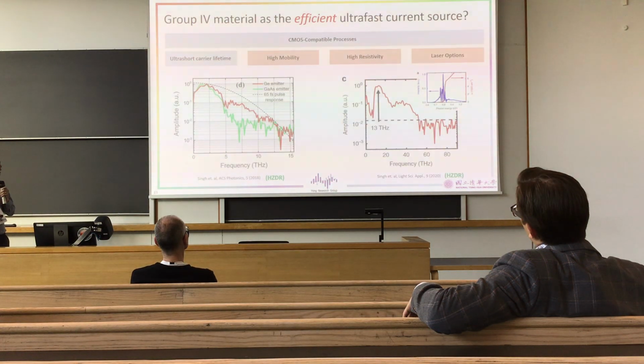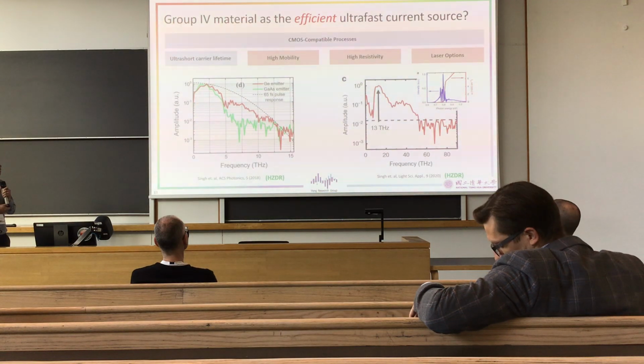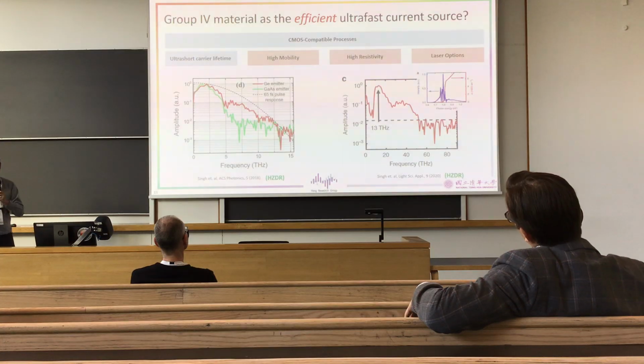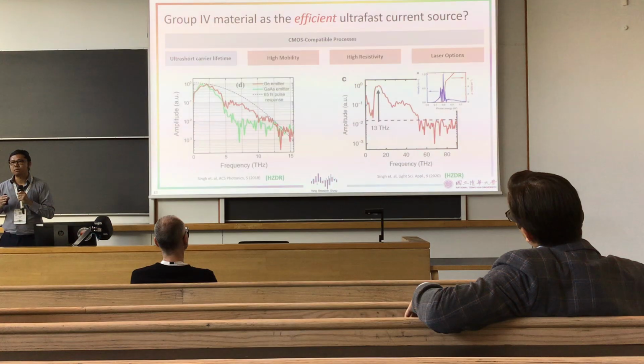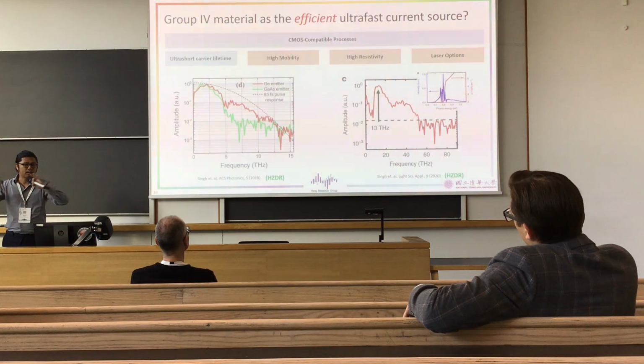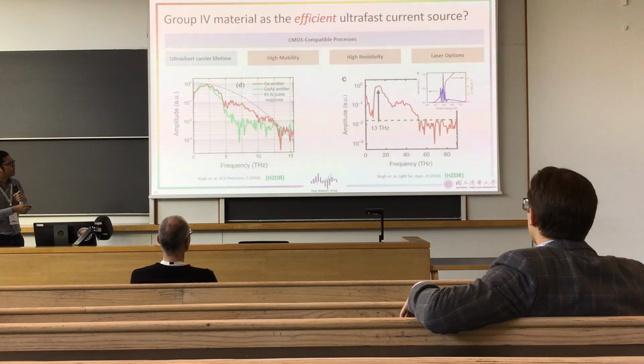Then, in 2018, the HZDR group demonstrated very high performance germanium terahertz PCAs. It's really good, and they even demonstrated very, very broadband terahertz radiation. But for germanium, the absorption above 1550 nanometers just dropped a lot. It's just at the band edge. So if you go with a short pulse, it means extending the wavelength range, so a loss of power, since it's just not getting absorbed.